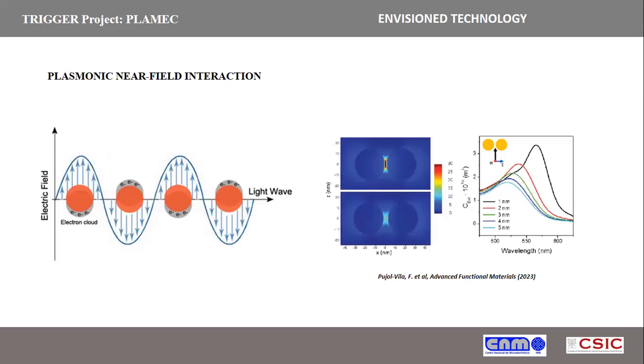So, motivated by these issues and inspired by the idea that the plasmonic near-field interaction is very, very sensitive to small changes in the interparticle distance. Sorry, maybe I should say that plasmonic near-field interaction is a coupling of the plasmonic fields between plasmonic nanostructures that is especially strong when the plasmonic nanostructures, for example, gold nanoparticles, are very, very close, closer than the diameter of the particle itself.